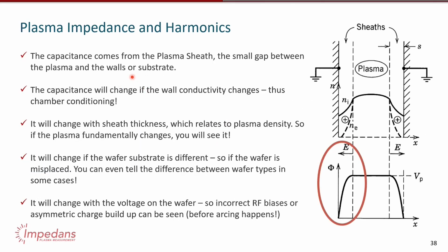So let's talk about capacitances inside a plasma chamber. A major source of capacitance are the plasma sheaths. So plasmas form a gap between the central bulk of the plasma and the walls and the wafer and so on. There's a little gap, and that's called the sheath. So, let's say looking at the walls, if wall conductivity changes, because you're etching or conditioning the chamber, or you're etching something and it's sputtering onto the chamber, you get changes in the wall conductivity, and you get changes in the capacitance. So that means you can actually monitor whether a chamber is conditioned correctly or not, based on the values you get from the VI probe.